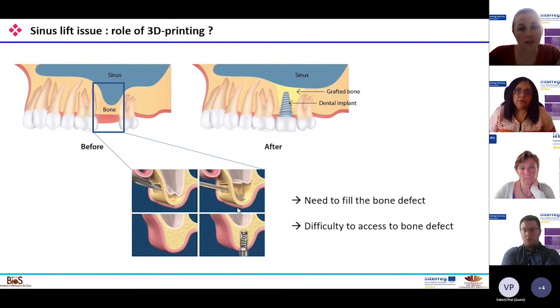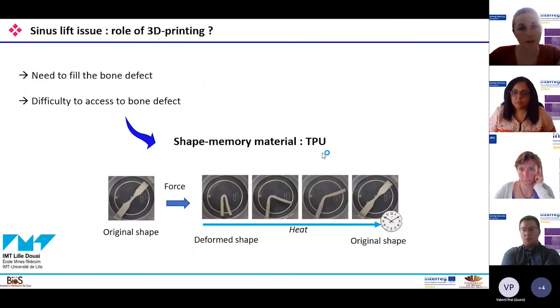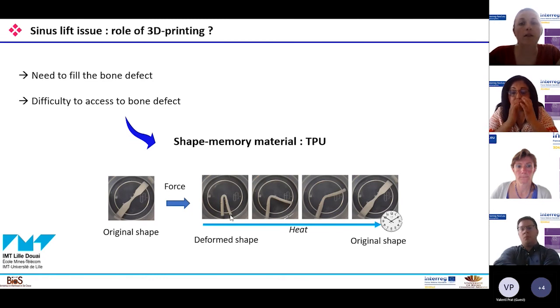However, the issue we have is that the access to the bone defect, as you can see here, is very small, and the defect to regenerate is bigger than the access. So our idea was to use a shape memory material. We used TPU, thermoplastic polyurethane. This is a polymer which can be deformed with a force, as you can see here, and with a stimulus, for example heat for the TPU, it can find back its original form.